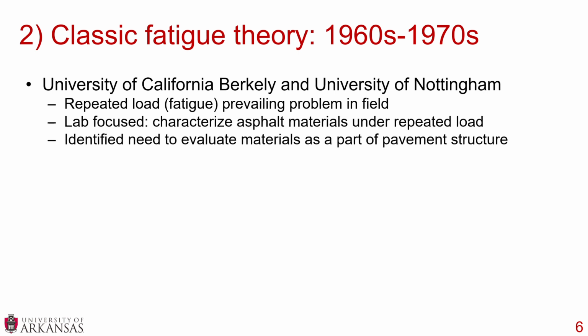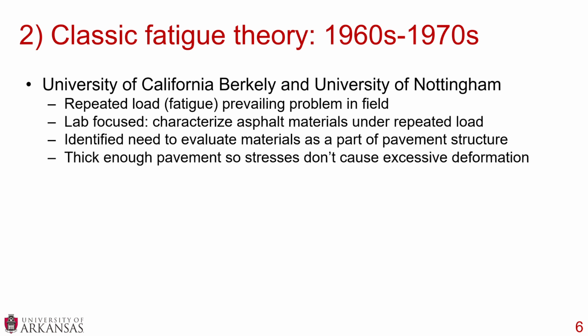This was lab focused, and what they did is they characterized asphalt materials under repeated load, but they also at the same time identified the need to evaluate the materials as part of a pavement structure. So from the get-go, they recognized that we had these material behaviors and we needed to link that to pavement structures. And they knew that we needed a thick enough pavement so the stresses in the pavement structure did not cause excessive deformation, which would lead to fatigue cracking.